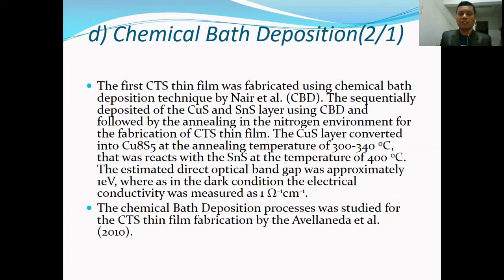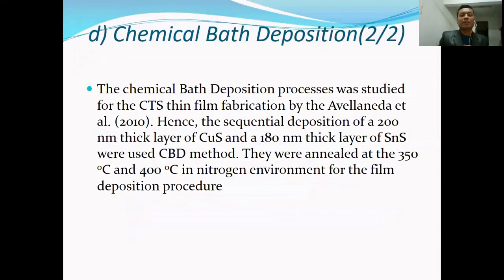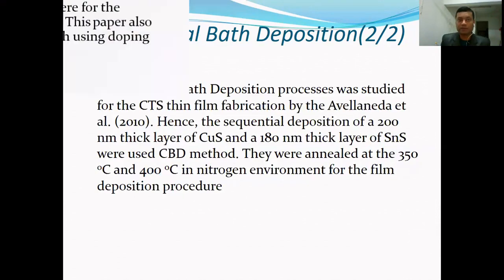The chemical deposition process was studied for CTS thin film fabrication by Avellaneda et al., 2010. Here, the sequential deposition of a 200 nanometer thick layer of copper sulfide and a 180 nanometer thick layer of tin sulfide was used by the CBD method. There were 350 degrees Celsius and 400 degrees Celsius temperatures in a nitrogen environment for the film deposition process.